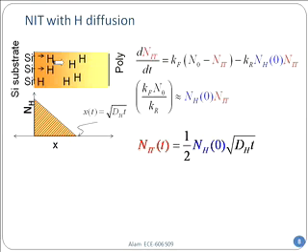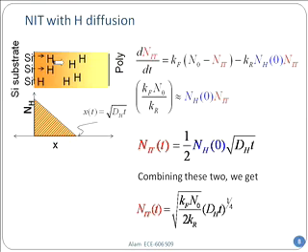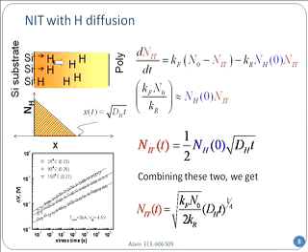So now I have two equations and two unknowns, right? And that immediately tells me the number of broken bonds goes as, so that was the experiment, by the way, and look at that, t to the power 1/4. So it is telling you, by this very simple 3-line algebra, no rocket science here, the number of bonds that will be broken as a function of time. Let's say this is 1 month after you bought your computer, 5 months after you bought your computer, so you put 5 months in time t, and that will tell you how many bonds got broken.